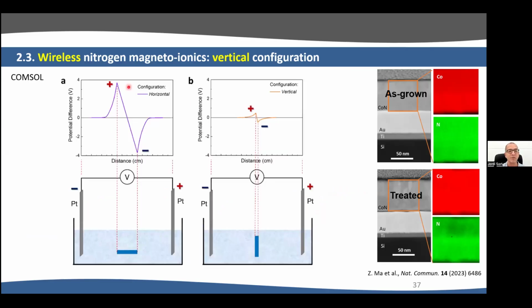Because as I mentioned before, in the horizontal configuration, we have, and this comes from simulation, a strong difference of potential between the left and the right sides of the sample. When we stop the voltage, this tends to discharge, and this discharging causes the reverse reaction, and the nitrogen just moves laterally. Here, the difference of potential between the two sides of the sample is very small, and virtually there is no reverse reaction, and the effects are permanent. Again, here you can see this typical planar front of nitrogen Magneto-Ionics.